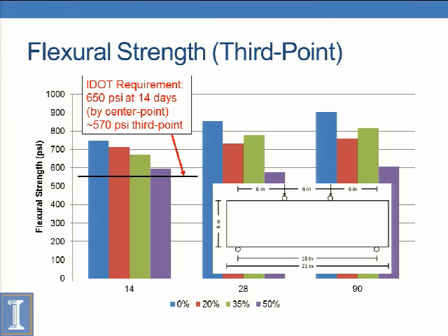But if you assume the typical difference in center point versus third point loading of 15%, we can see that about 570 psi is what IDOT would say. They don't have a spec on third point, but we're just assuming here. So pretty much we could pass the IDOT spec for flexural strength, most likely.